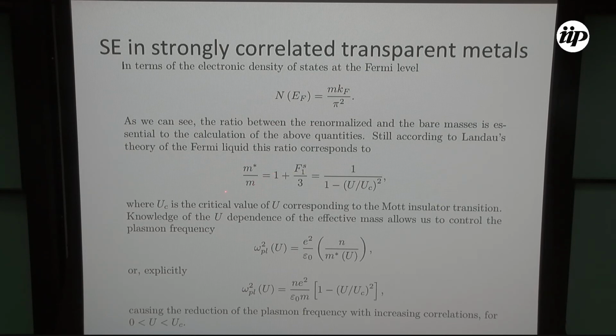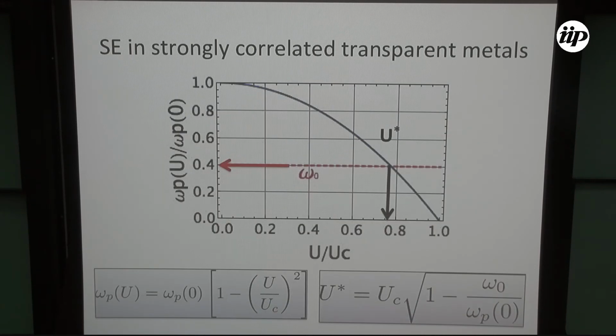How the effective mass renormalizes. It renormalizes in terms of the Landau parameter F1S, and it's simply 1 divided by 1 minus the ratio to the second power. Now we plug this into the expression for the plasmon frequency, and we obtain this expression. Remember that the coefficient is simply the plasmon frequency at 0 correlation, so we get some curve that decreases from 1. The ratio between the correlated plasmon frequency and the free plasmon frequency decreases from 1 to 0 at the Mott-insulator transition. We want to be away from this Mott-insulator transition.